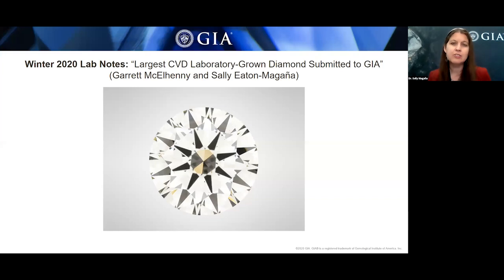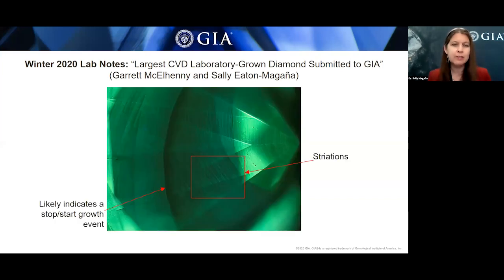Now, the next slide shows a DiamondView image, which indicates several diagnostic features. It shows striations, which are the results of CVD diamonds growing up atom by atom. And if you cut across those, then it can resemble a staircase. The DiamondView image also indicates a stop-start growth event. Both of these features help confirm the CVD growth origin. Additionally, the fluorescence color, green, shows that this CVD grown diamond was subsequently HPHT treated. This treatment is generally intended to reduce the brown coloration present in many as-grown CVD laboratory-grown diamonds.